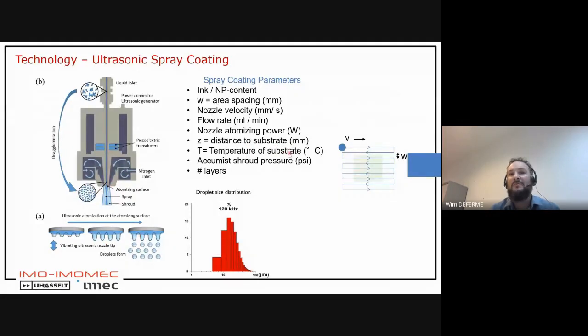Of course, the temperature of the substrate plays an important role because we use liquids, we use solvents that can evaporate during flight, but also on impact with the substrate if your temperature is higher than room temperature. And we also have the shroud pressure itself, so the pressure of the carrier gas that we apply to bring these droplets towards the substrate, because of course if you apply higher pressures, the velocity of the droplets towards the substrate will also increase.